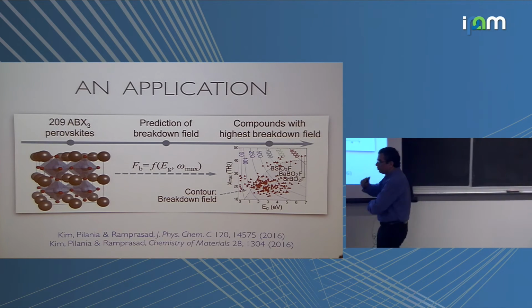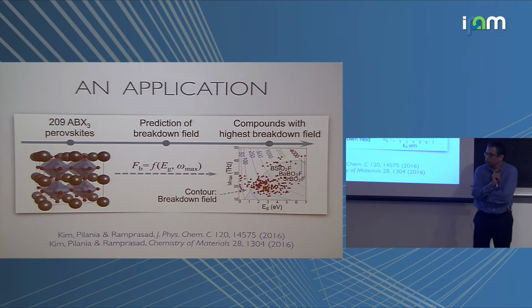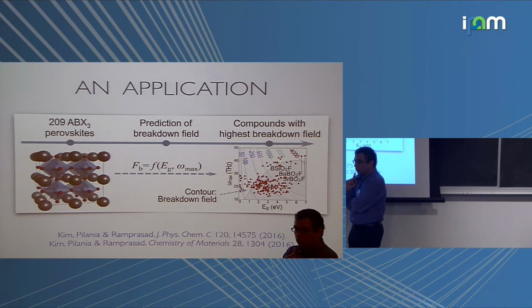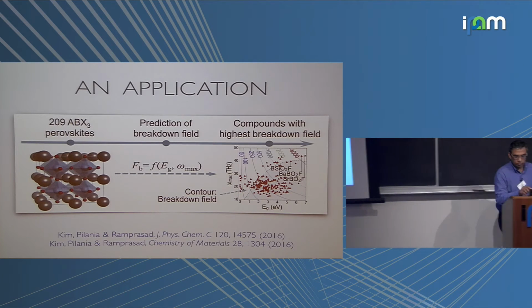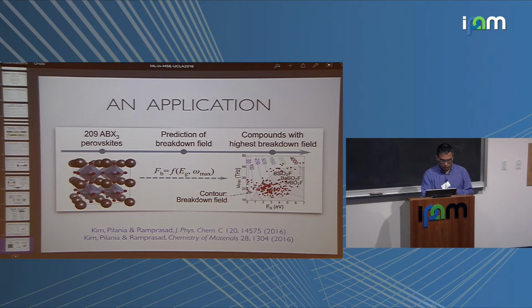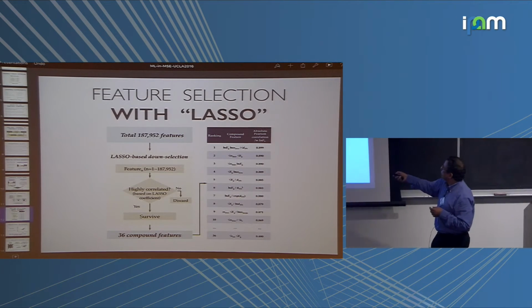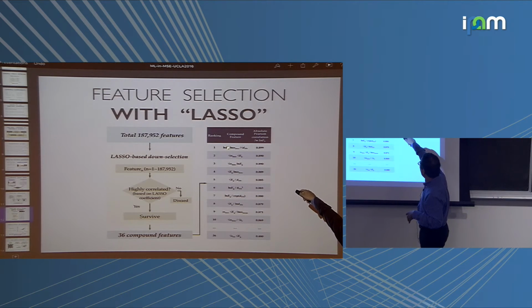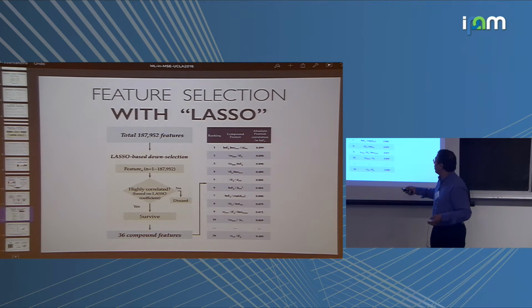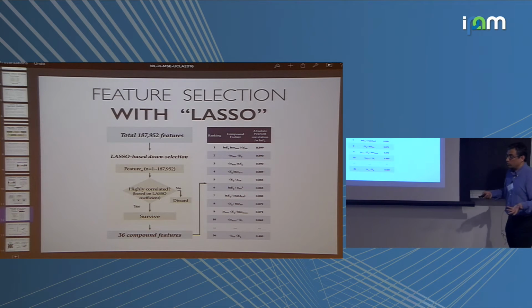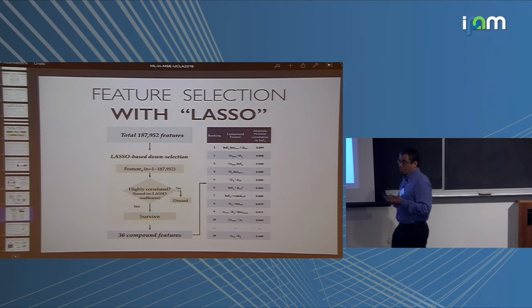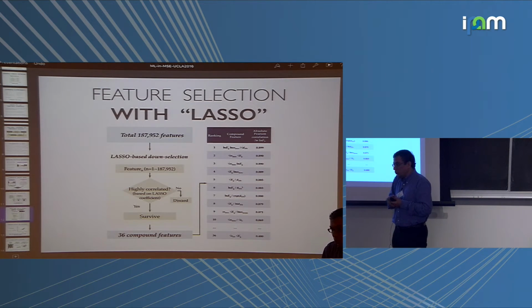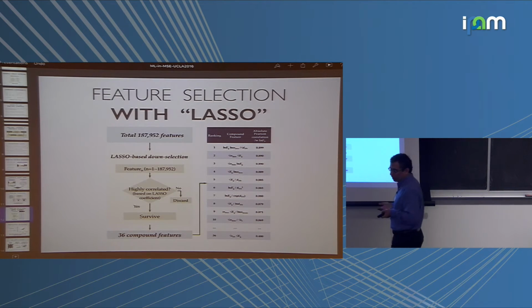Excuse me, how do the 36 differ? More by the functions or more by the primary features? Both. Some by the physics, right? Because they really probe different aspects of the physics. Correct. That's why I felt actually combining them makes a lot of sense. Actually, let's go back and look at this thing here. So Anatole, your question. Phonon cutoff, band gap. In the first few features, the phonon cutoff and band gap persist, and I believe this is what Matthias is saying. If you take the first 5, for example, phonon cutoff and band gap keep showing up. As you go further down, you get the nearest neighbors and mean phonon frequency and other properties begin to emerge. But the top 5 are dominated by the phonon cutoff and the band gap. Which probably is actually close to a law. At least it makes sense that these things determine the breakdown. Yes, sure. But then that particular formula, I cannot argue that specific formula is a law.